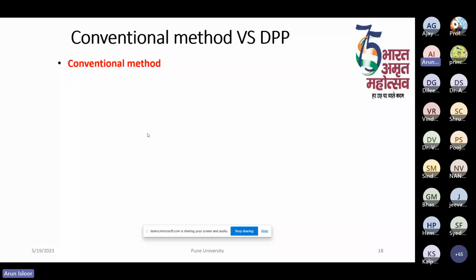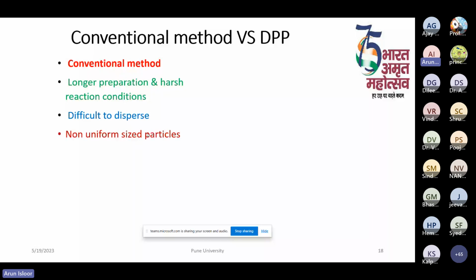So for the fabrication method, let us see what the general drawbacks are in the conventional method for nanomaterial fabrication. Generally, there are longer preparation times and harsh reaction conditions, and the materials are difficult to disperse during the reaction. The size is also non-uniform in a few of the cases, not all the cases. And further modification, if you want to introduce some functionality on nanoparticles synthesized by the conventional method, is very difficult. Generally it ends up with a gel or coagulum, so in such cases the isolation of the material is also difficult.